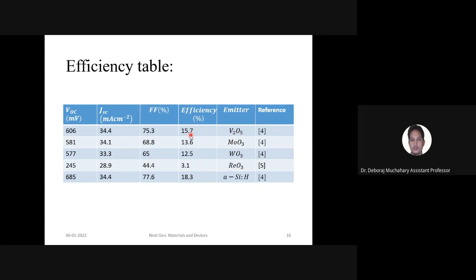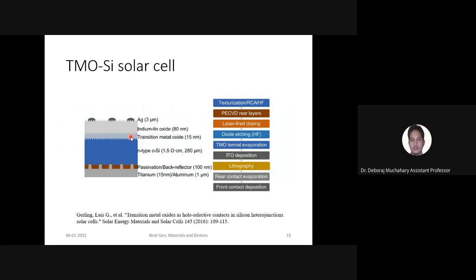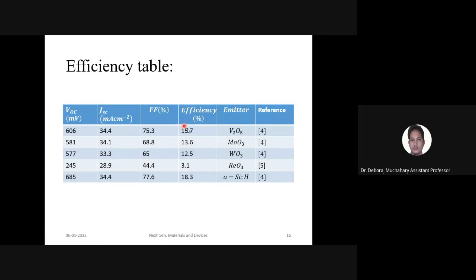But the highest efficiency they have got is with V2O5, and the reason is the high electrical conductivity of this layer. V2O5 has higher conductivity as compared to ReO3. Another reason is the recombination at the interface. Here we have this transition metal oxide and silicon, so at this interface, this heterojunction, definitely some defects are there. Due to that defect, these different efficiencies are found. The best one they have mentioned is V2O5, and the worst one is ReO3.